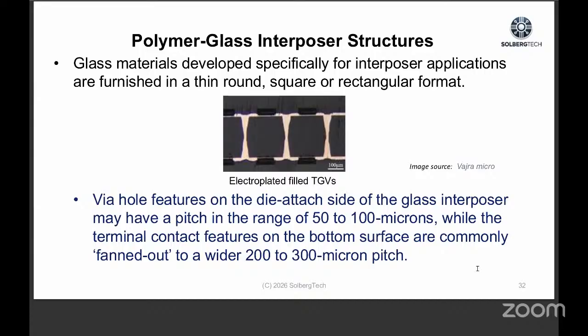And you see that taper that's in the middle. They go through this initially with a very small hole with a laser, and they come back and do a chemical plasma etching process to open it up and then plate through. So it's not like a drilled hole so much as it just has a unique shape to it, but it does furnish continuity. Next.